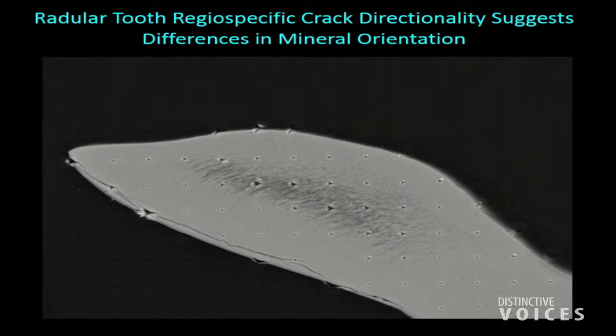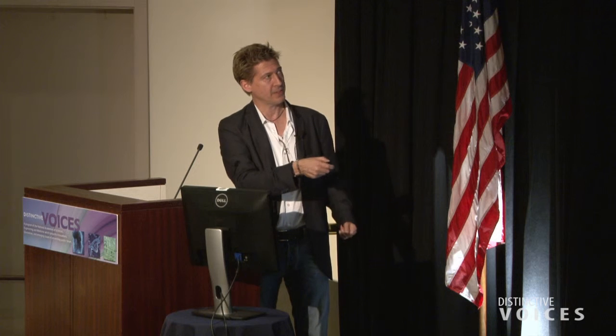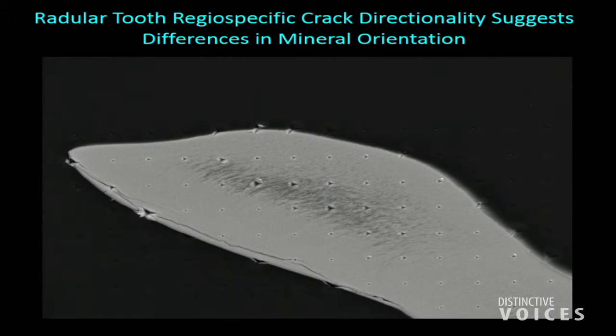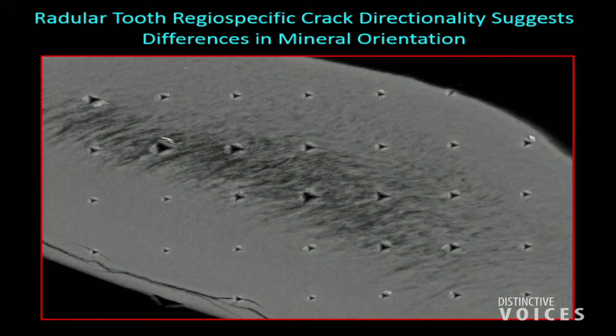So we go to these nano indents that I've made. Remember, I pushed that little diamond probe and I got that little map with all those dots. So these are the little dots. If you look up close, this would be, for example, the core of the tooth. Because it's a softer material, the probe goes in deeper. On the outside, it's a harder material. The probe does not penetrate as deeply. But we interestingly found that there are cracks that all are along the side of the tooth.